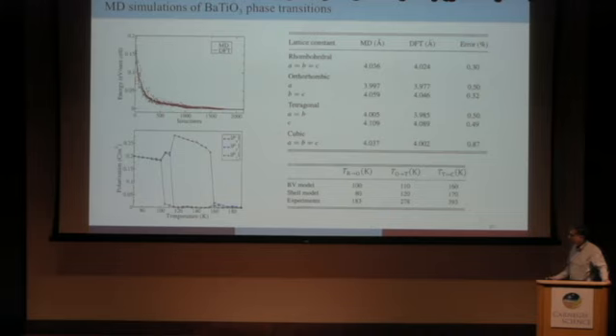The temperature is all too small compared to experiment, but many of the local structures appear to be quite accurate. And it actually, the point is it's designed to reproduce first principles calculations. It's not fit to experiment. And if you do molecular dynamics with density functional theory, you would also get similar suppression of Curie temperatures.